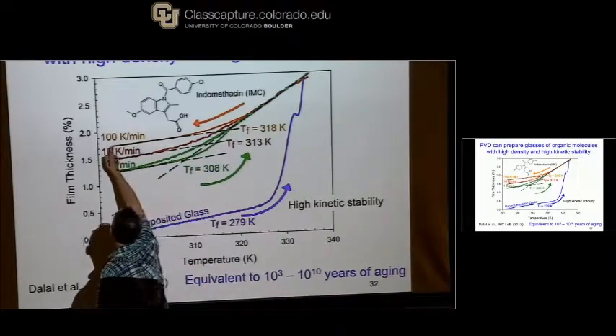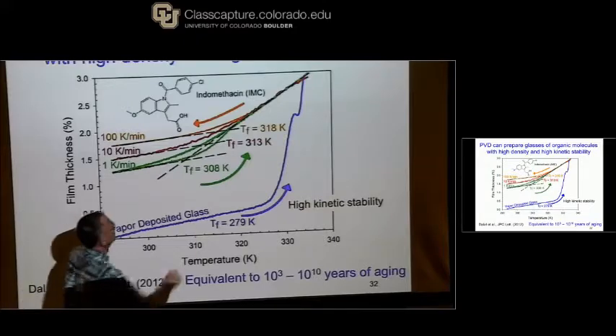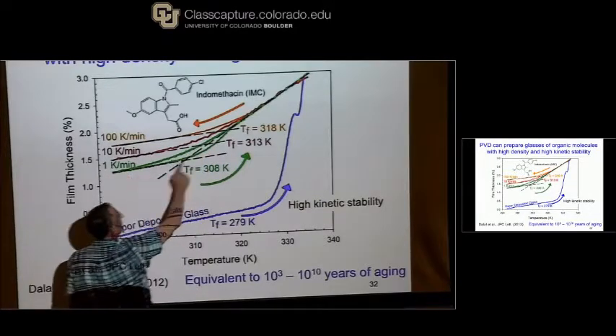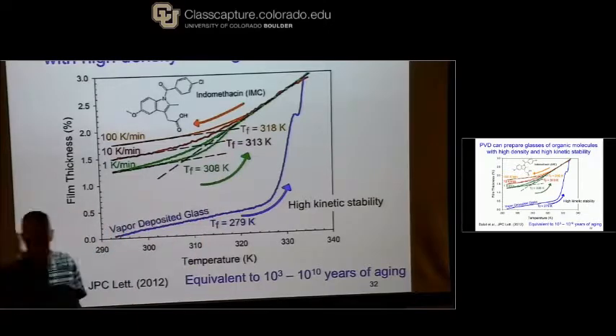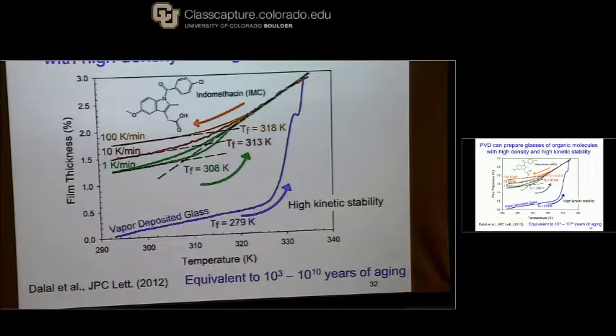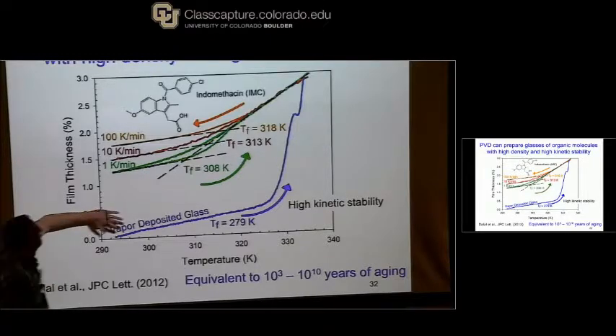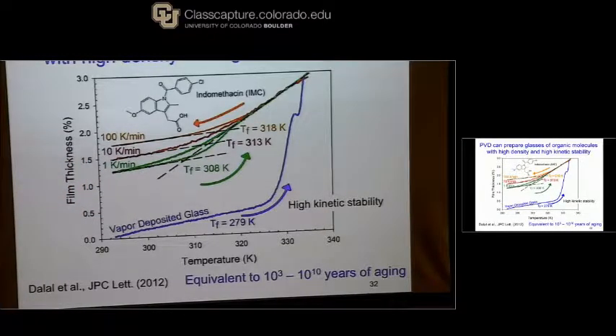If I take that liquid and I cool it at 100 Kelvin per minute, I go down this orange line. If I cool it at 10 Kelvin per minute, I go down this line. If I cool it at 1 Kelvin per minute, I go down this line. If I immediately reheat, I get that hysteresis. Someone asked about the hysteresis that you see when you scan up and down through the glass transition. And so there it is. It's shown in the green curves. So everything that's up here should look familiar to you. You cool faster, you stay in equilibrium longer, you get a thinner film, a more dense film. So hopefully everybody's okay with that.